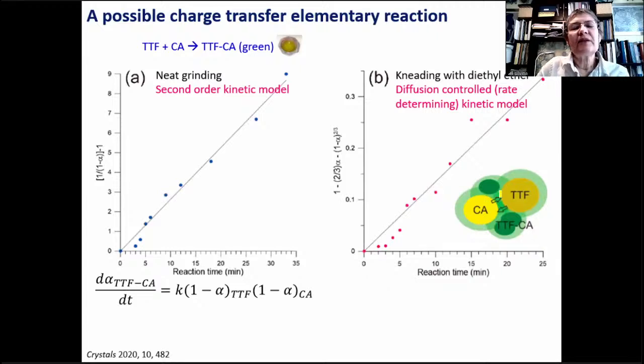So this reaction, the formation of the green tetrathiafulvalene chloranil, I consider it a good candidate for an elementary reaction by mechanochemistry. Since a second order kinetic model may imply that only molecules of the electron donor and the electron acceptor meet, forming the products, and there are no barriers for the nucleation or crystallization of the product from the reaction mixture.